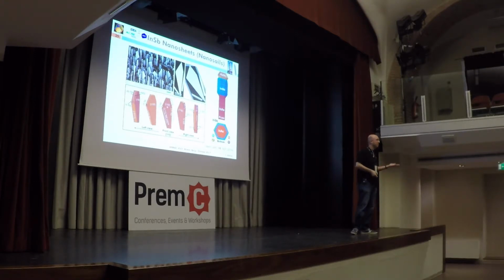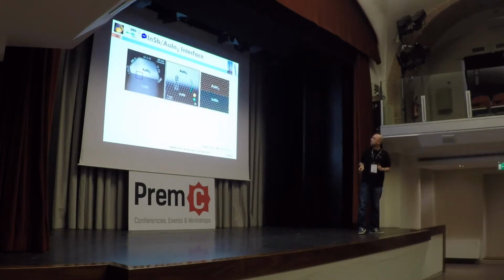And you can tell me, how is this 111 layer terminated? It's terminated in antimony. So the anion is also focusing and letting the material, after breaking the symmetry, create this 111 facet terminated in the anion phase, and then you can see how the material can grow again to that side. So because of that, we can create these perfect nanomembranes.